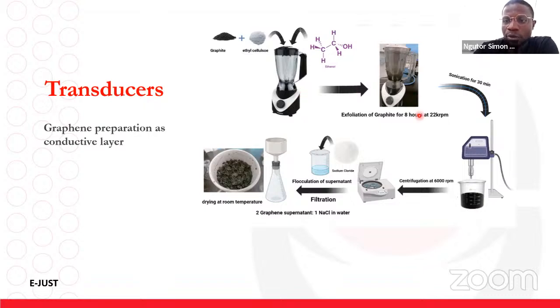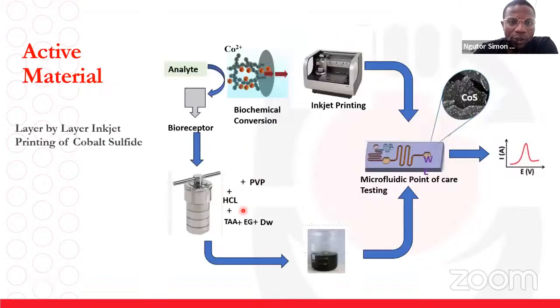And then we're able to collect this, which is sonicated and then centrifuged at 6,000 RPM to remove the supernatant. We only collected the supernatant and then added sodium chloride to make it flocculate. After the flocculation stayed for like 24 hours, we filtered it, and here we collected the graphene. So this is the fabrication step for the active material.